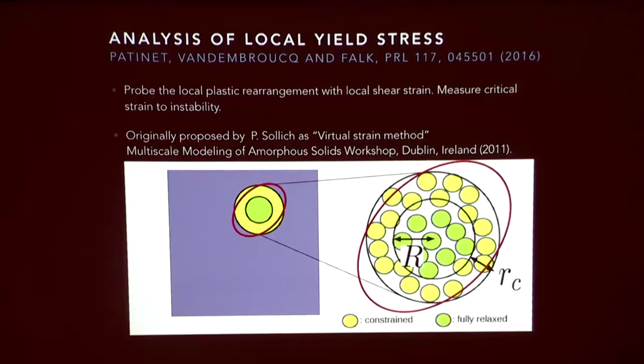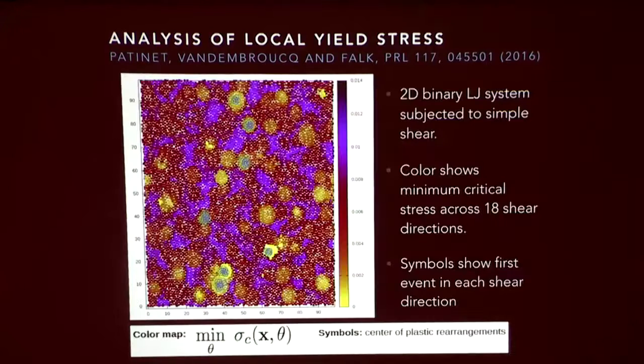So we chose that length scale and tested different length scales—that ended up being a decent one. When we do that, what we're measuring is, along different orientations, what stress we have to impose to get a plastic event, while constraining it to be local, since everything outside of this region is just not allowed to happen. And we could do that in different orientations.